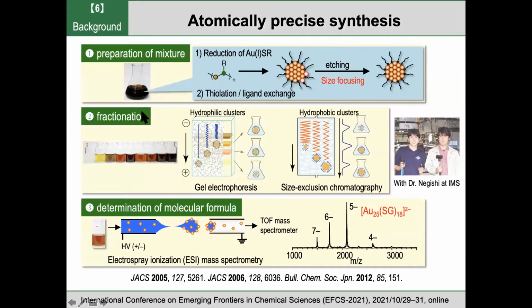And then the last step is the determination of the molecular formula of the cluster compound in individual solutions by using ESI mass spectrometry, which Professor Pradeep explained to you. This is a non-destructive method to determine the molecular weight of the cluster compound in solution. For example, by analyzing this kind of data, we can say that the cluster contains 25 gold atoms and 18 thiolate ligands. So we can determine the chemical composition of individual solutions. Okay, so we have a method to synthesize the clusters with atomic resolution.